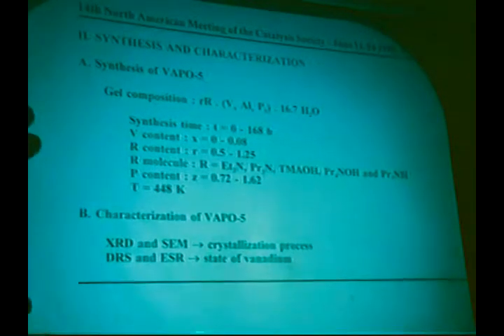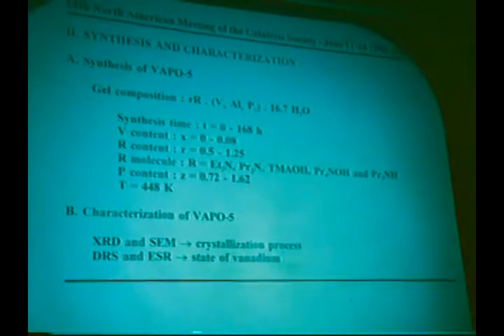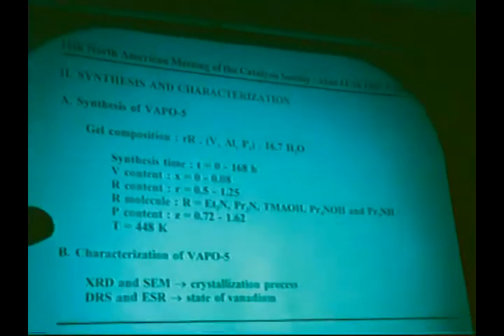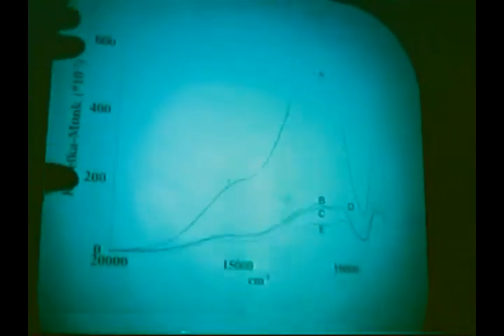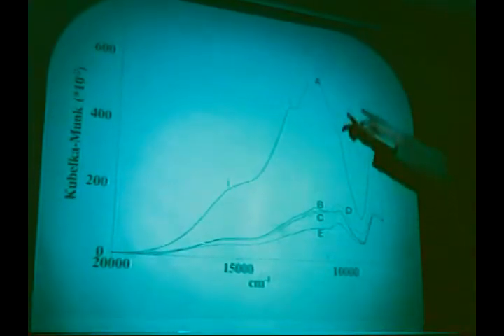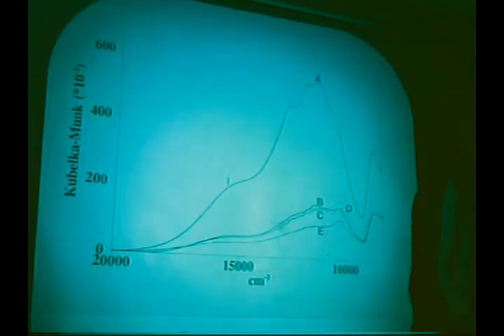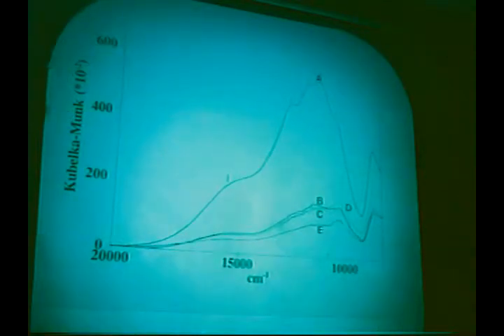I want to discuss the chemistry of the initial gels. These gels are light blue to blue and are characterized by the following diffuse reflectance spectra. Diffuse reflectance spectra show a main band around 13,000 reciprocal centimeter, but in any case, they are broad and encompass several bands.